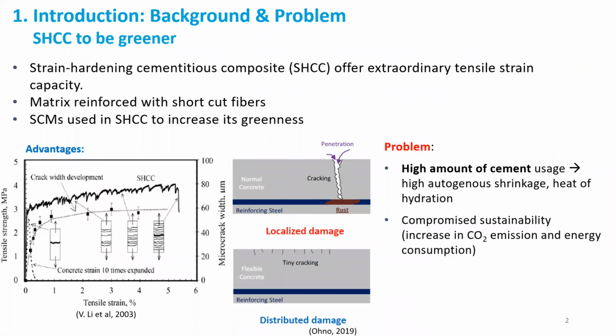The strain-hardening cementitious composite, SHCC, offers extraordinary tensile strain capacity, as shown in the figure on the left. It has almost several hundred times higher strain capacity than conventional concrete. The matrix of SHCC is also reinforced with short-cut fibers, which enable the multiple cracking property. This is beneficial since it leads to tiny cracks with very small crack width at the surface instead of one single crack, which is beneficial for durability.